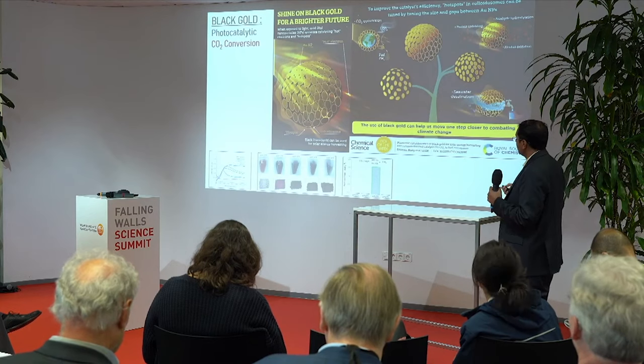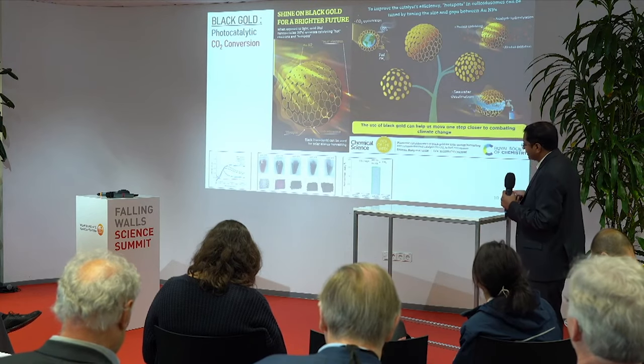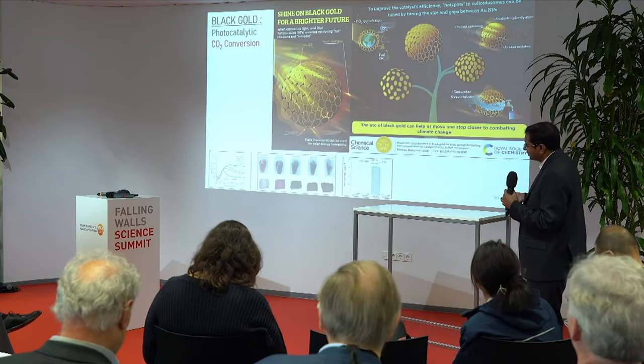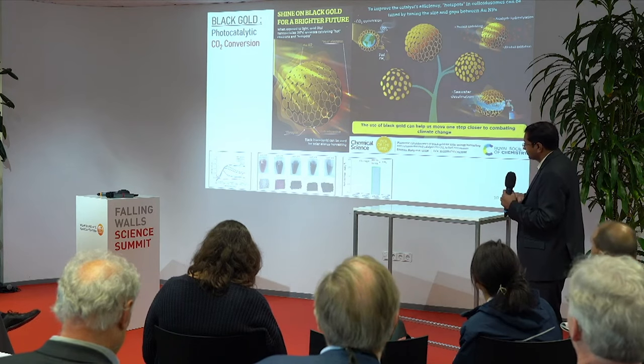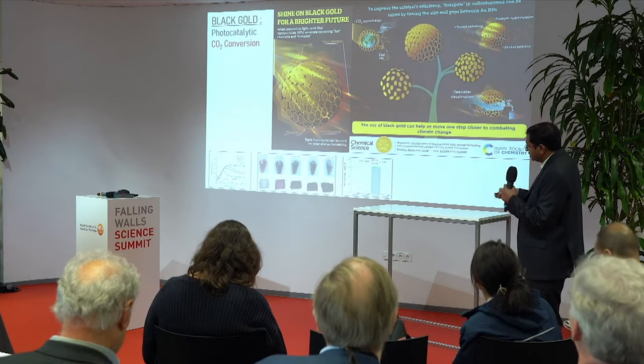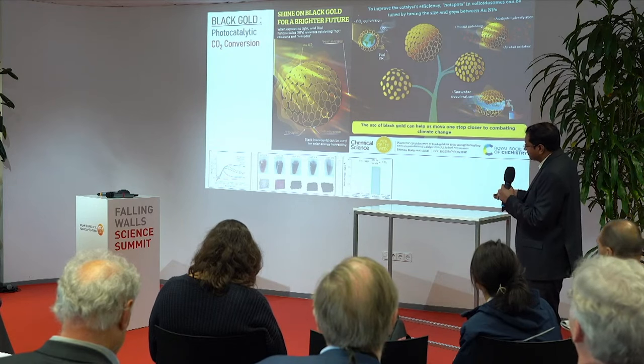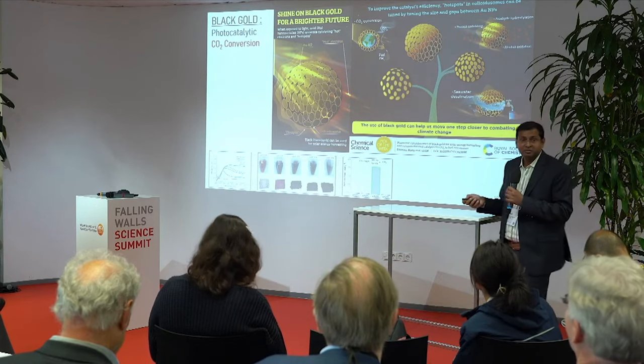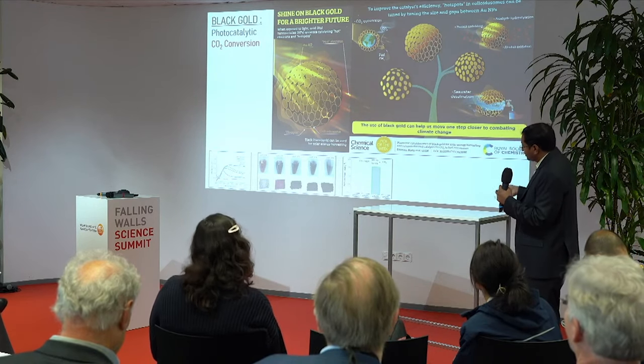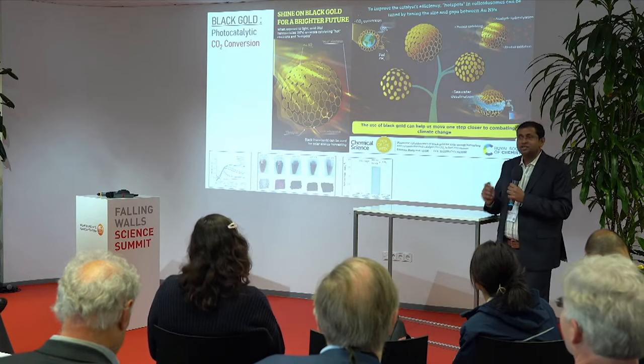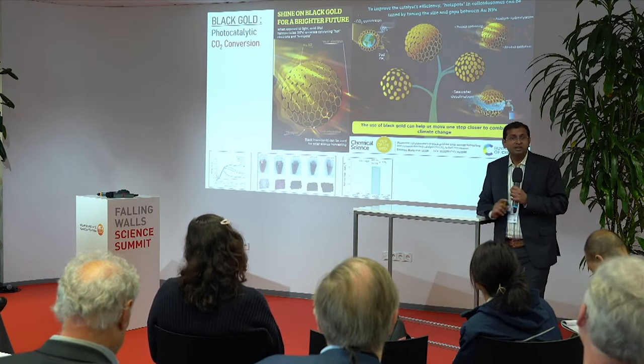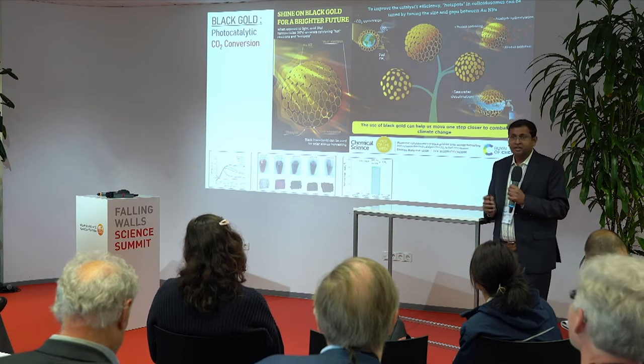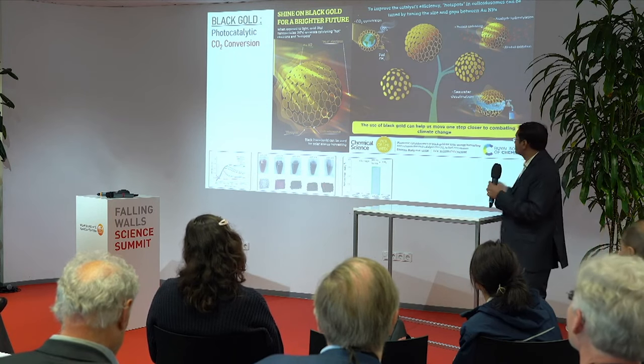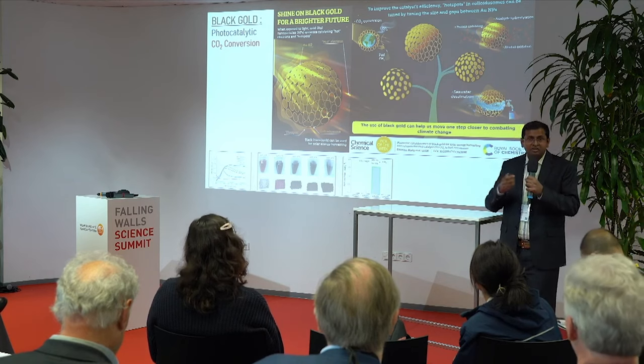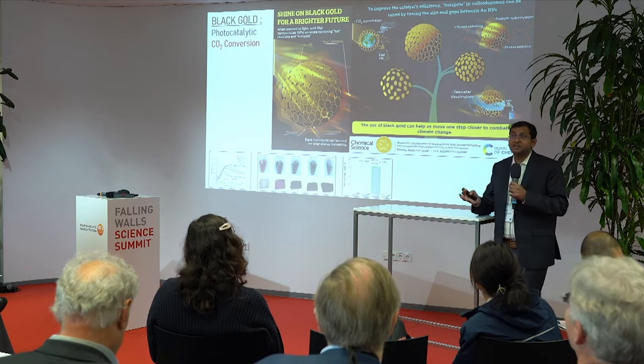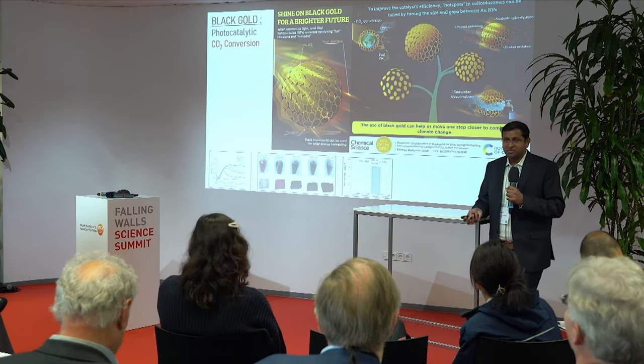And now you can see, look at the color. If you take a simple gold nanoparticle, it harvests around 550 nanometer. But by simply tuning the gaps, you now get a broadband light absorption from 400 nanometer to 1100 nanometer. In the physical way, the gold becomes black. It is still gold, still metallic gold, no change in the oxidation state. No functionalization, nothing. It's simply the particle size distribution and the plasmonic coupling, which gives you the black gold, which harvests the entire solar photon. So after making this material, we were very excited.